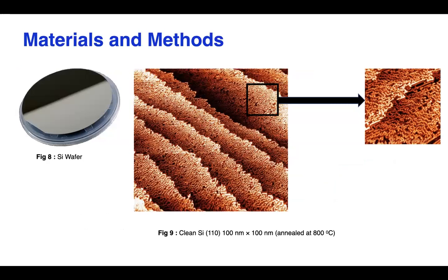Okay, let me get back to my business now. As I mentioned earlier, I worked on the silicon 110 surface. First of all, before we do anything, we have to clean the surface and get the reconstructed silicon 110 surface. So I used silicon wafers. Here in figure 8, we have to cut the sample out of this silicon wafer. That sample should exactly match the sample holder which we are going to put inside the vacuum chamber. A normal sample size is length 10 to 15 millimeters, and width 4 to 5 millimeters.